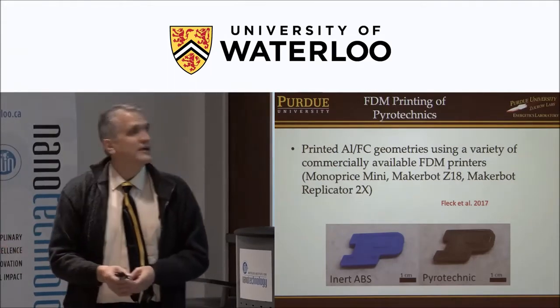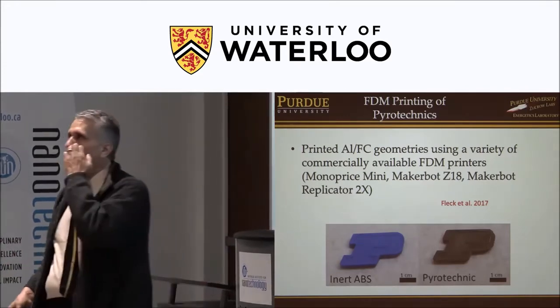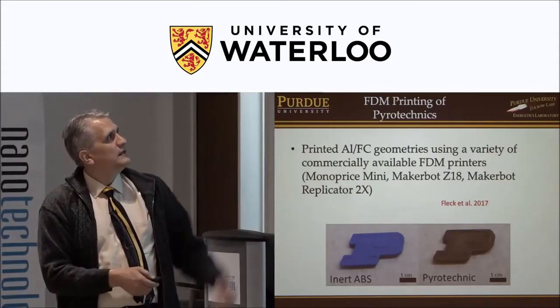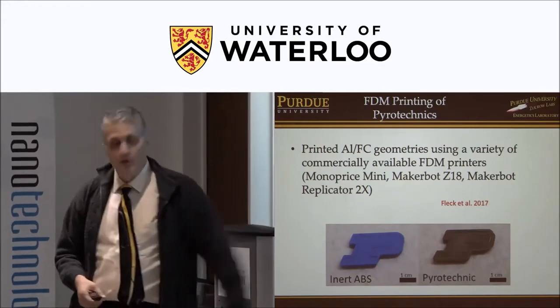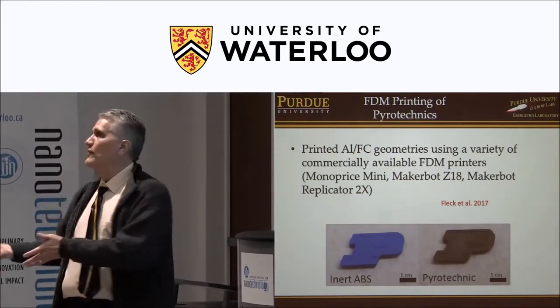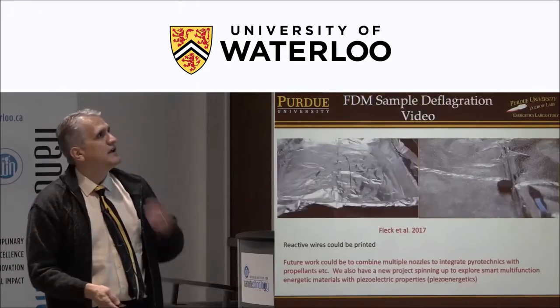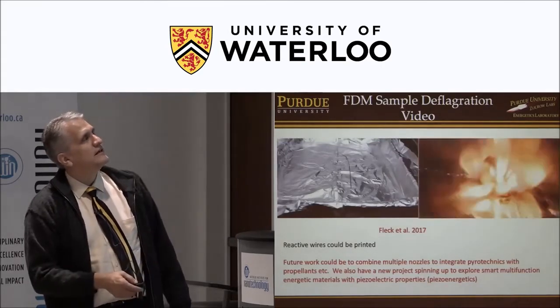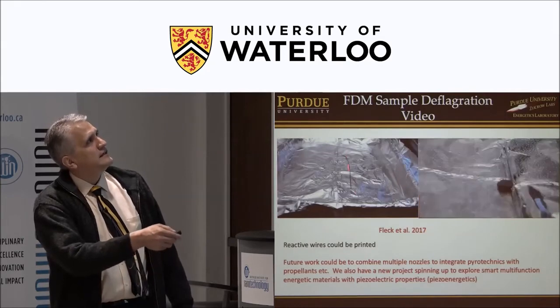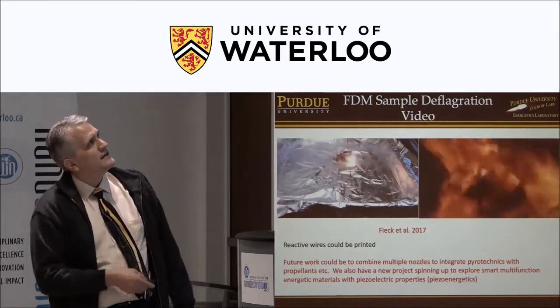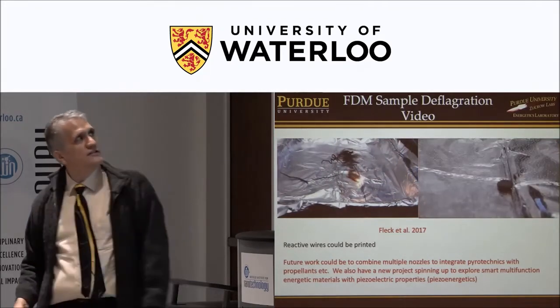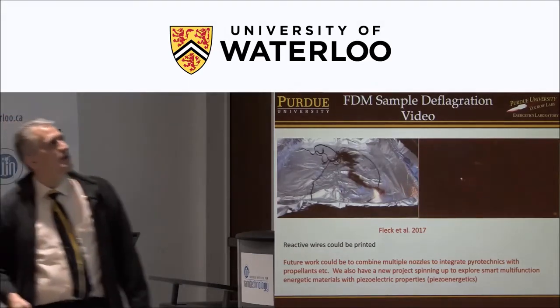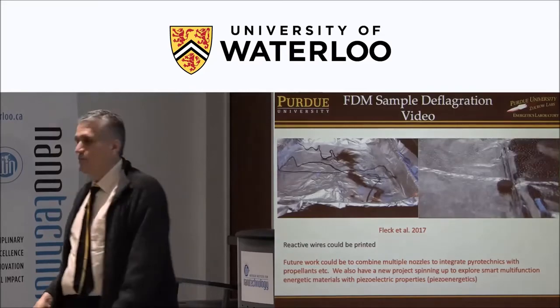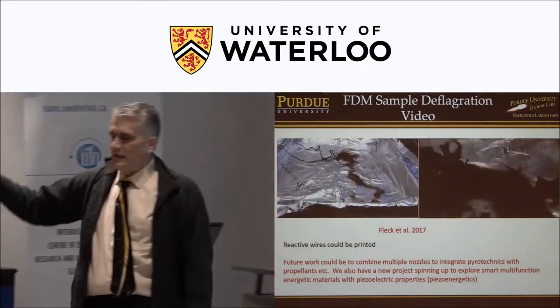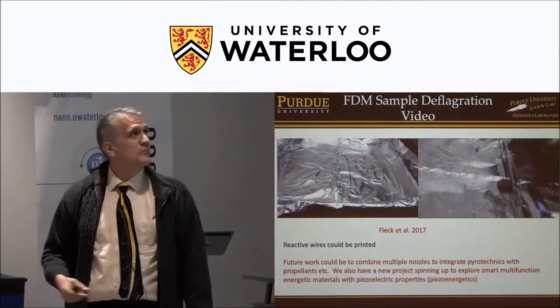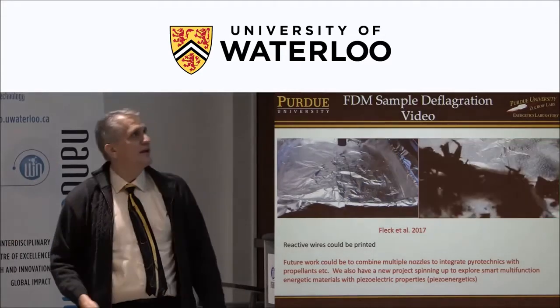That's just a commercial filament maker. You can buy those actually to recycle your printed parts if you want, and make new filament to print in your FDM printer. But we use it to make a novel filament. And then we can take that filament, put it into a MakerBot or whatever, and print up reactive parts. This is a little printed puck. It shows that it's reactive. And this is actually just a filament here that you ignite. It's producing a lot of carbonaceous and also aluminum fluoride products. So as you see here, we could print reactive wires. We're moving towards, as I showed you, reactive wires, if you will, in solid propellants. You can think about printing the solid propellant and the reactive wire together.